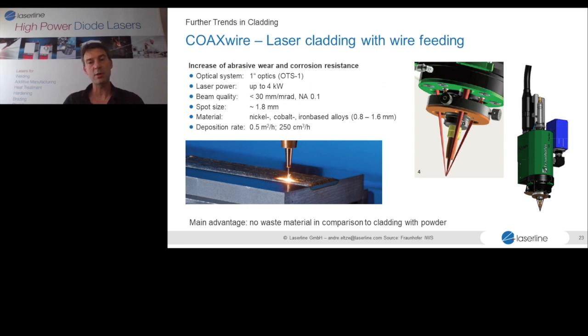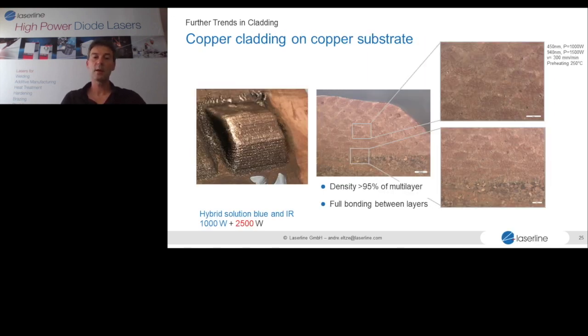We can see more and more applications looking at wire-based cladding. So we are also able at much higher efficiency to add wire into the surface of a material, in particular for 3D printing as an example. We see the trend, you've already seen this from the brake disc application, the trend in cladding moves more and more towards very high power. So we've been able to show extremely high deposition rate. In this case, it says 35 kilogram per hour deposition of cladding powder using 50 kilowatt output power. So we see the trend in this direction. What is also interesting, a new laser based on blue diodes. In this case, it's a hybrid process, infrared and blue diode laser used as a combined process for cladding of copper powder onto a copper substrate, something that would not work with another wavelength simply because of the problem of absorption.